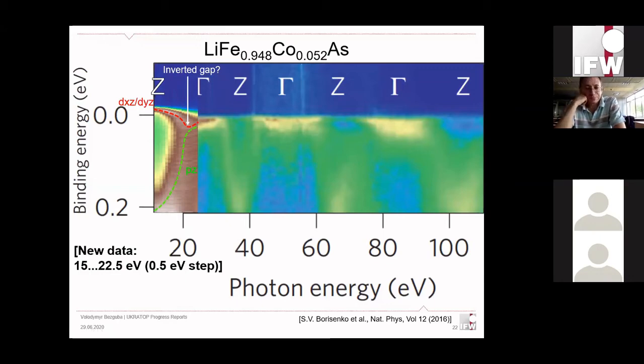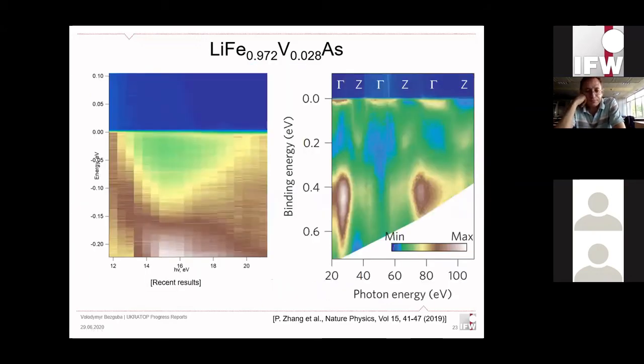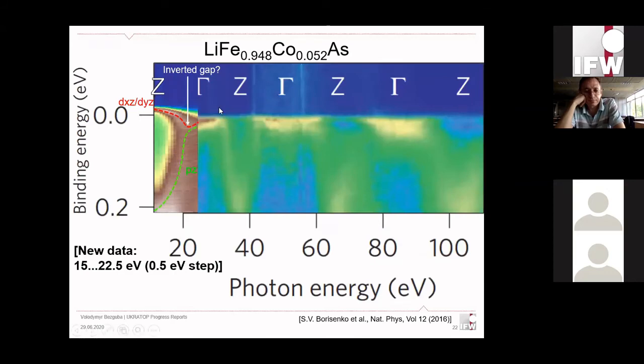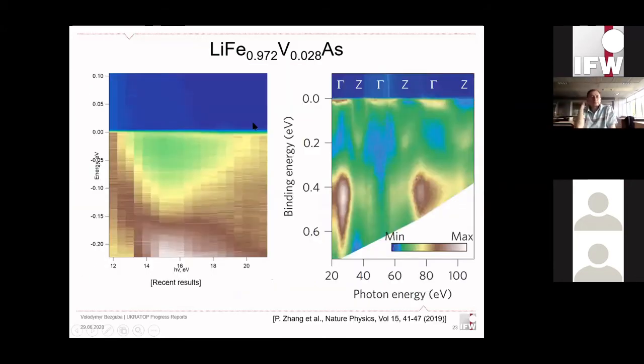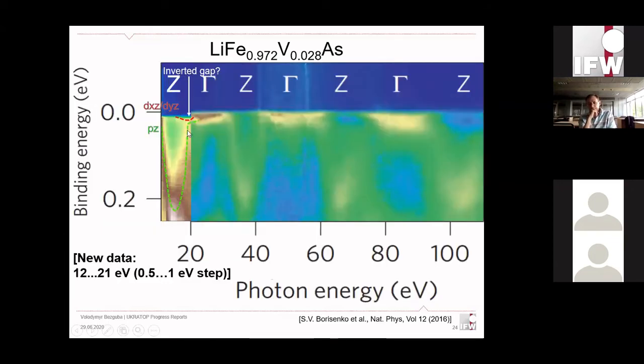The same was done for the vanadium sample doped with holes. In this case, you might notice that the Fermi levels don't correspond. It's because cobalt is electron doping, like I said before, so it should be shifted up. With vanadium, we get it shifted down. This is the detailed zoomed in picture of the map we complement to this old map. And this is the overall picture in which, again, we see signs of something going on, but we don't see the inverted gap itself. It's not possible to map it, unfortunately.